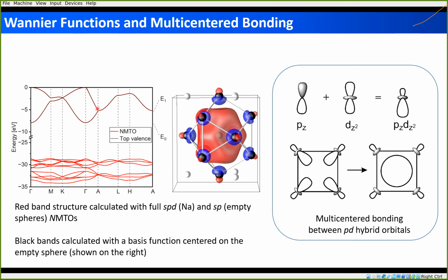And here I show the actual full band structure with the downfolded band structure that one would get from this Wannier function. We note that it does look quite a lot like a blob around the non-nuclear attractor site, except that it has these tails on the 11 sodium atoms that are around this kind of cluster.